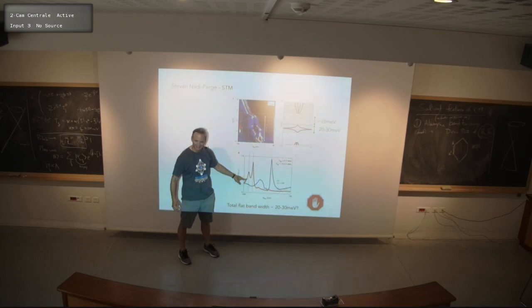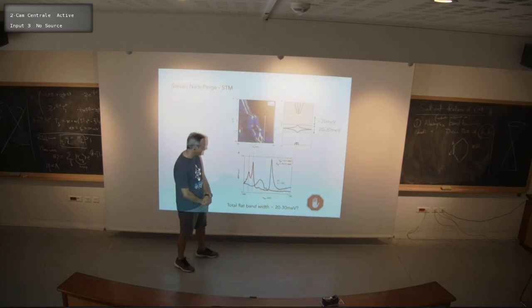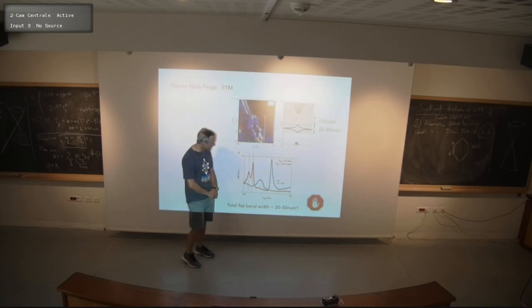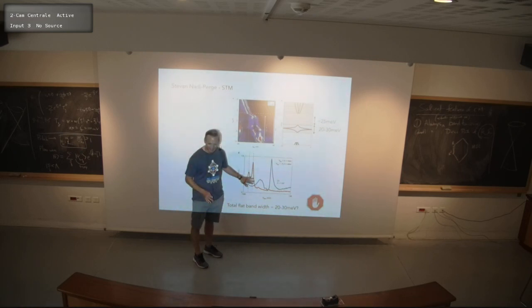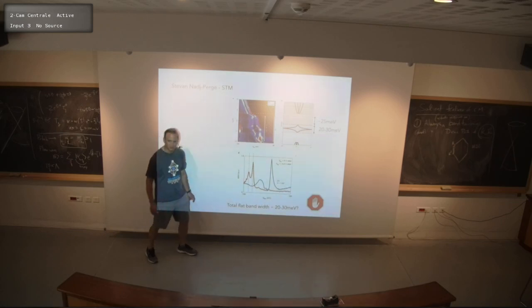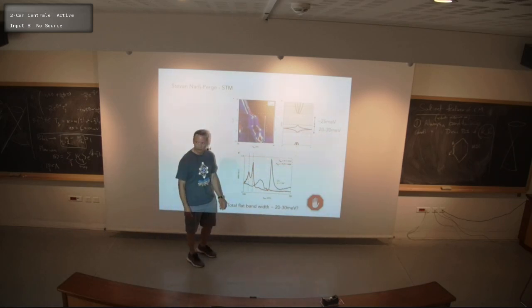It's not a momentum resolved measure, so maybe you're thinking in terms of an ARPES measurement or something like that. And this is a very broad thing. I think there are many reasons for the broadening. Among other things, these are quite inhomogeneous systems. But I think the effect you're really seeing here is something like a Van Hove singularity. It wouldn't be sharp in any case. This is not something that in any measurement would be a delta function because it's just a local density of states. So I think it's quite difficult to extract a mass from this. Okay, but that's a good question. Other questions?